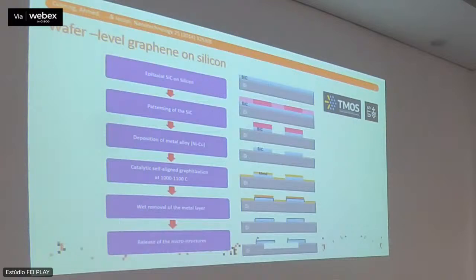Okay, so this is really, I would say, the most appealing part of this methodology: we're able to be site selective. What that means is that because we're using a silicon carbide film on silicon, we can pre-pattern the silicon carbide on silicon in any pattern we want to achieve, including pillars and such. Then we deposit that metal alloy as a blanket layer, with no additional lithography steps. And then the whole system will recrystallize only where you have the carbon source, so only where you have the initial silicon carbide that was present.